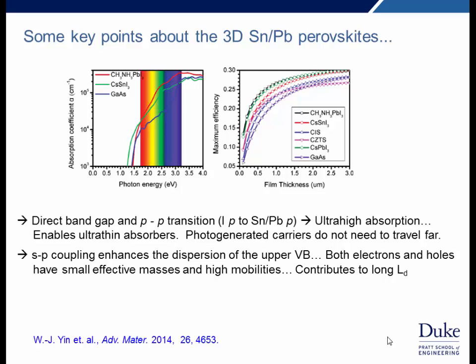And the reason for its high performance or high suitability for PV relates to, first of all, it's got a direct band gap, but also the nature of the states close to the conduction and valence band edges is P-like in character, and this gives rise to a large joint density of states, which in turn leads to high absorption. And as we heard, this enables the ultra-thin absorbers, meaning that the photogenerated carriers do not need to travel very far. Also, a high degree of sp coupling enhances the dispersion of the upper valence band, which means that not only the electrons but also the holes can have a small effective mass and high mobilities, and this contributes to long diffusion lengths in the device.